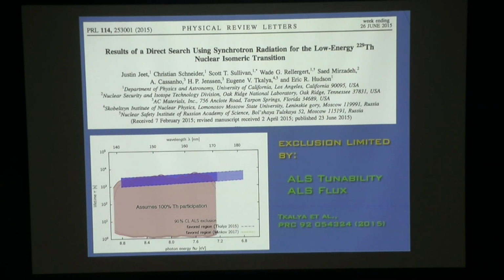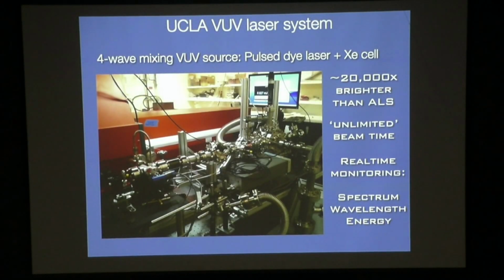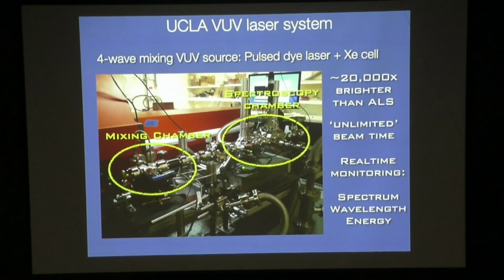So what did we do? We went back to UCLA and said, I guess we have to build that laser. So that 3 to 4 year search, we're just going to have to do it. So we took a laser. It's based on 4-wave mixing of a couple pulse dye lasers. There's a cell of xenon here where some VUV light is made. And it comes to the same chamber we used at the advanced light source. And it's exactly the same idea, just to shine a laser on, turn it off, and look for fluorescence. It couldn't be simpler. The problem was that we would have to run 24/7 almost for like 3 years.